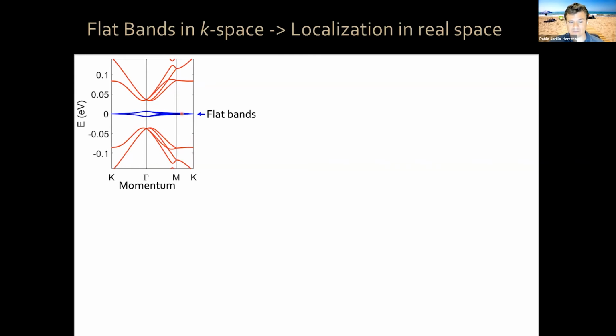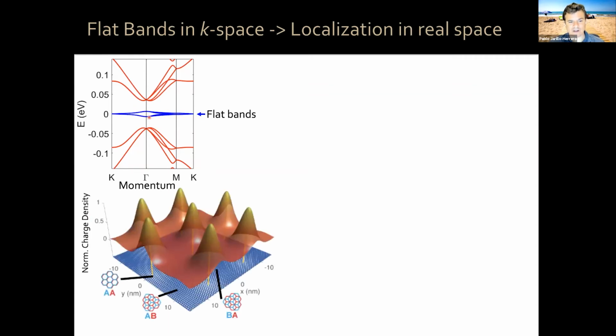Now, this is how they look in momentum space. If you want to see where the charge goes when you put electrons in these flat bands, you have to do a Fourier transform to go to real space. And then what happens is that when electrons are in these flat bands, they like to sit in these regions where locally the two graphene sheets appear to be exactly aligned and on top of each other. We call this AA stacking, okay? These regions are tunnel coupled by regions of AB and BA stacking, where due to the small angle of rotation, the graphene sublattices from layer 1 and layer 2 get out of registry into this AB and BA configuration.